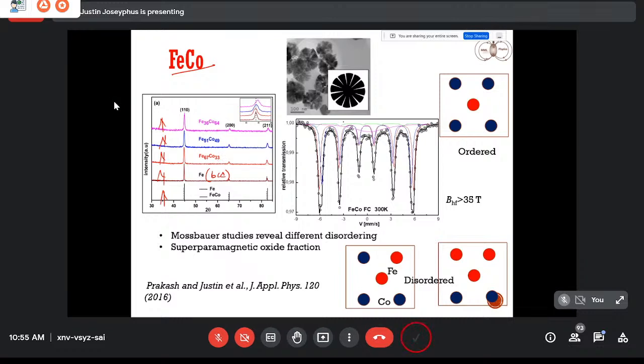And we characterized it using Mossbauer spectroscopy. And the iron cobalt was flower-like in shape, with an average size of around 150 nanometer. And when we characterized using Mossbauer spectroscopy, it was confirmed that it was iron cobalt from the hyperfine field. Okay. So a 6-line pattern. So it is ferromagnetic, with a hyperfine field showing a value greater than 350 kilo-oersted or 35 Tesla, and it was also shown that we have a superparamagnetic fraction from the double-line pattern.